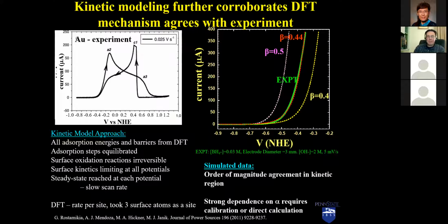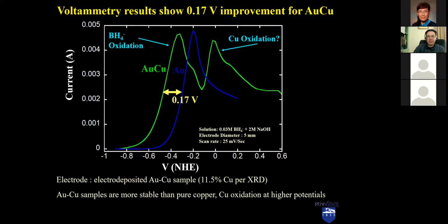And then this is one example where my lab was successful in designing a better catalyst. We then looked at how we can balance the fact that we need to bind the borohydride a bit more strongly, but not too strongly, because if it dissociates too easily, you get a competitive hydrogen evolution reaction. We computationally predicted that a gold copper bimetallic surface would have about a quarter volt shift. And then we experimentally measured about a 0.17 volt shift in improving the electrocatalysis with gold copper for borohydride oxidation.